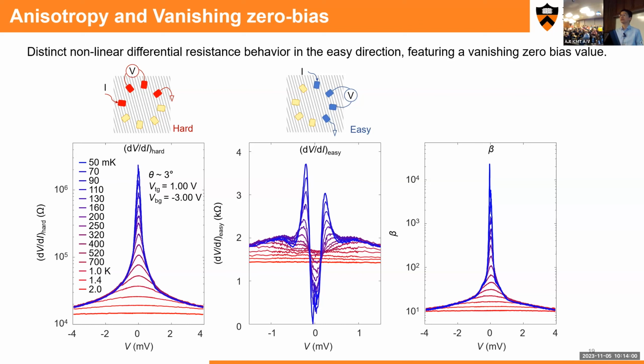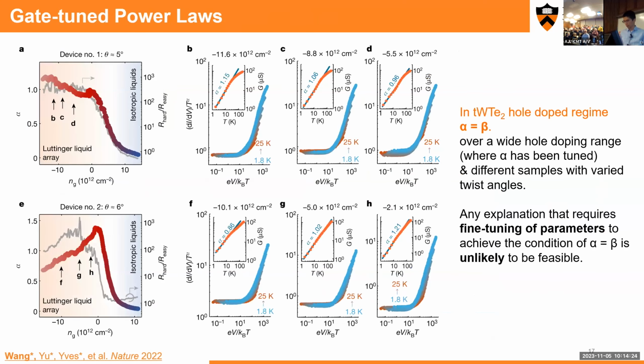The question is related: does one understand on what the alpha depends? You have the one example with the twist angle, 3 degrees, where alpha was 1.5. Does one have at least a quantitative understanding of what the reference alpha was and how it changed? That's a great question. First of all, by tuning the gating, we can change the alpha a little bit. This is what we show here in different angles. And second, if you change the twist angle, you can definitely change the alpha.